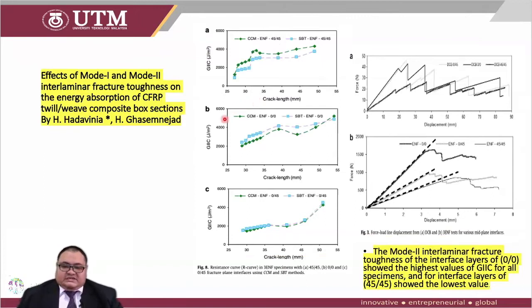This research shows that for mode 2 interlaminar fracture toughness, the interface layer 0/0 shows the highest value of G2 for all specimens, and the interface layer of 45/45 shows the lowest value. This is the effect of energy absorption.